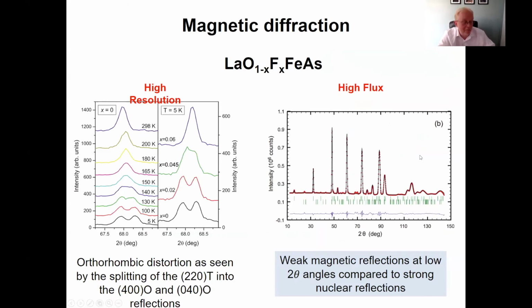We also do magnetic diffraction. If we just look at the graph on the left-hand side, here we have a compound where the dopant is 0, and as we cool it down, we see this peak resolves itself into 2 peaks.